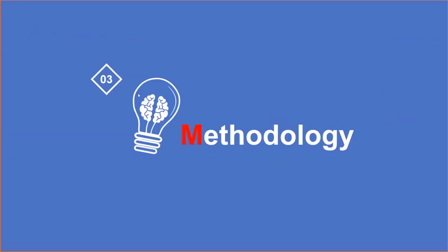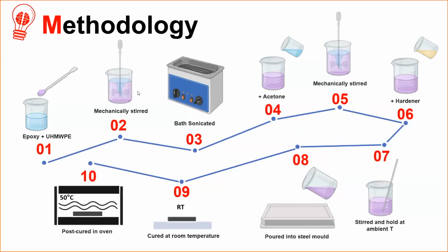Okay, for the methodology. After so many trial and error and preliminary studies on the method, this can be said to be the optimum method, which involves mechanical stirring of the epoxy and ultra-high molecular weight PE mixture, followed by sonication to further improve the dispersion and break down the agglomerated particles. Then the addition of acetone to lower the viscosity of the epoxy resin, and lastly, the addition of hardener to initiate the curing process. Next, the mixture was put into the mold, left to cure at room temperature for 24 hours before post-cure in an oven at 50 degrees C for another 24 hours.